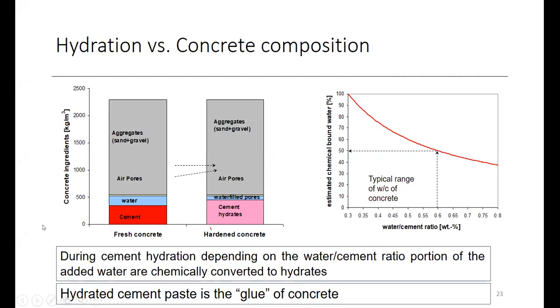During cement hydration, depending on the water-cement ratio, a portion of the added water will be chemically converted into the hydrates, as we discussed previously, CSH gel. And that hydrated cement paste is like the glue, acting as the bonding element of the concrete. It takes hold of all the sand and aggregates and makes them into one mixture of concrete. So cement paste acts as the glue of the concrete.